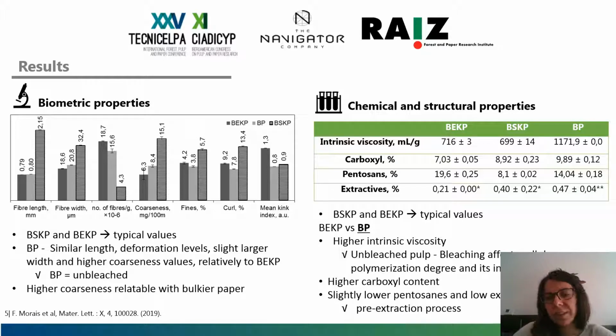As regards the chemical and structural properties, it was found that softwood and eucalyptus commercial pulps had typical values. Now looking at the bark pulp that we produced, it revealed a higher intrinsic viscosity when compared with eucalyptus pulp, which was attributed to the fact that it was unbleached pulp.